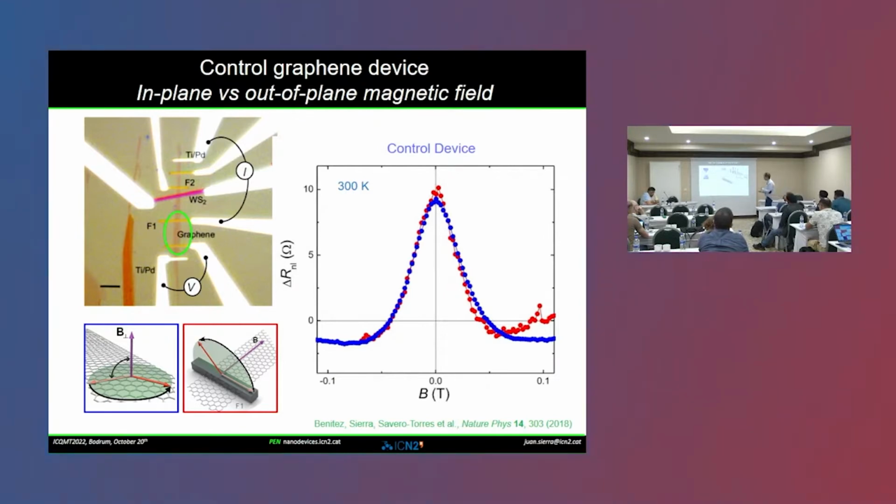So what more can we do with these devices? These experiments are based on spin to charge interconversion. Very briefly, there are two main mechanisms for converting charge into spin and spin into charge. One is the spin Hall effect. Everyone knows this: if you run a current through a high spin-orbit coupling material, you can generate a transversal spin current with the spins pointing out of plane. But you have a second mechanism here, the spin galvanic effect.